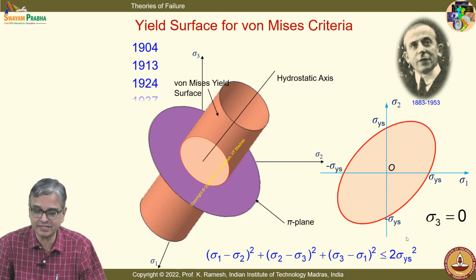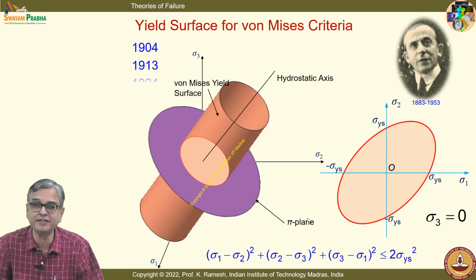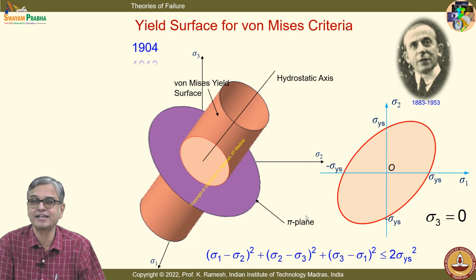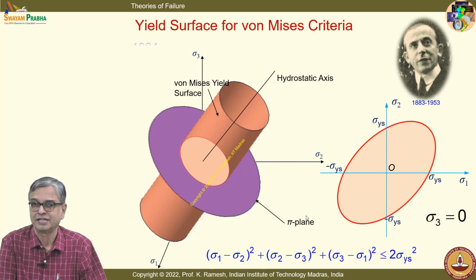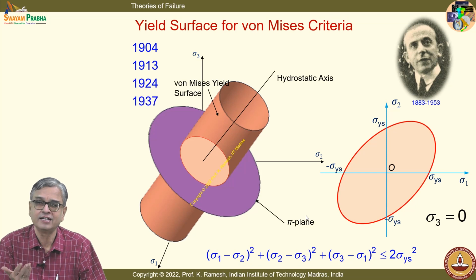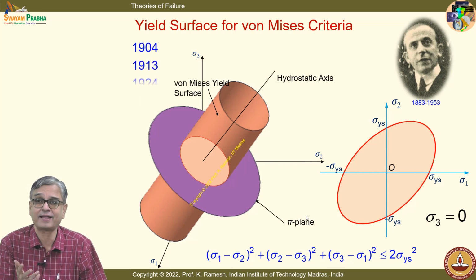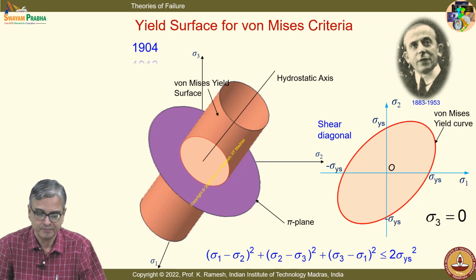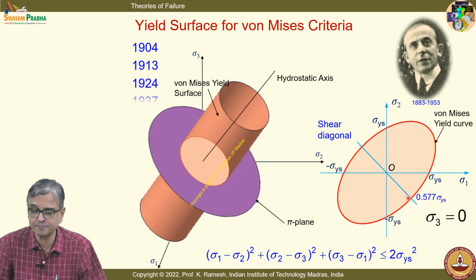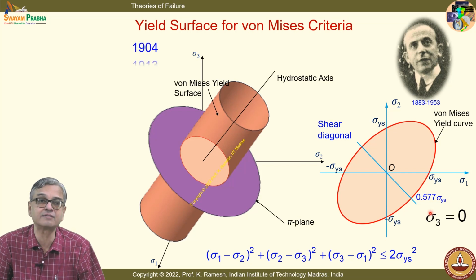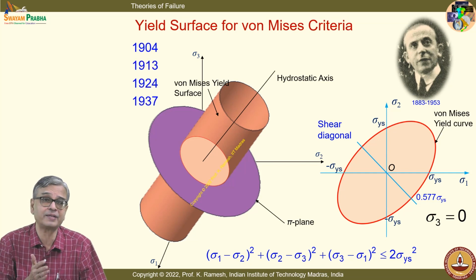Now, the next question is, I have shown von Mises independently. I have also shown Tresca independently. You have seen the shapes. It is a hexagonal cylinder in the case of Tresca. It is a circular cylinder in the case of von Mises. How do these two compare? That is also very interesting to see. And here also I have shown the shear diagonal, and here what it says is the shear diagonal value is higher than what is predicted by Tresca. It says it can go up to 0.577 sigma ys. So, there is a difference. You have multiple theories mainly because the material behavior is complex.